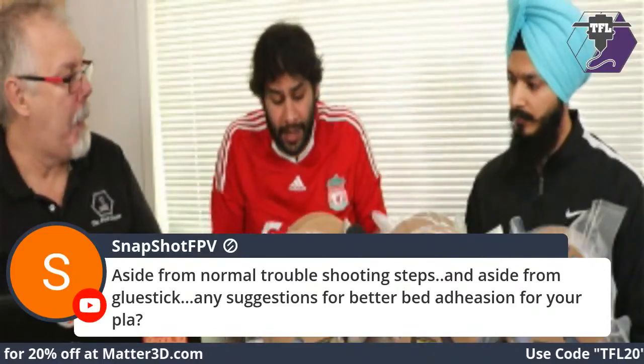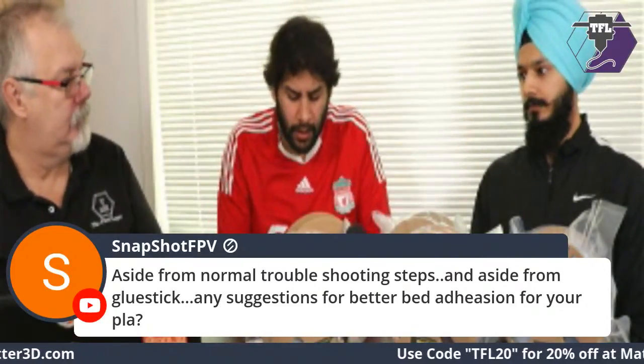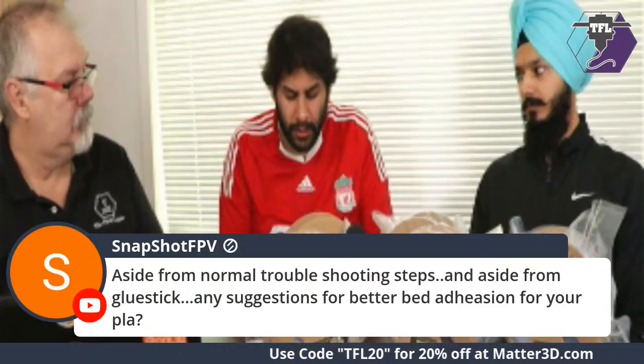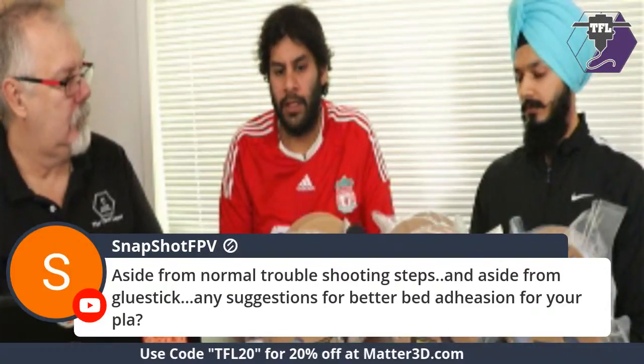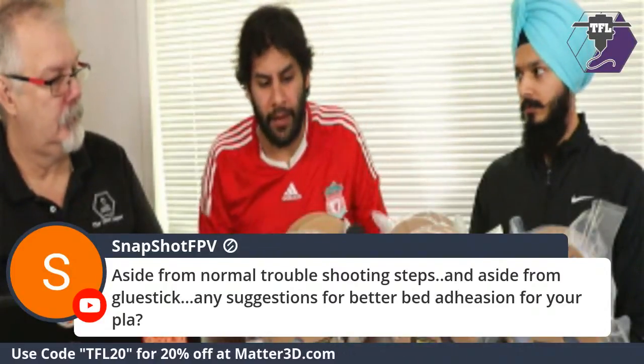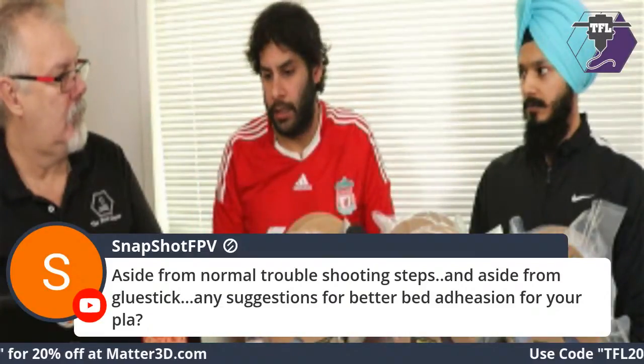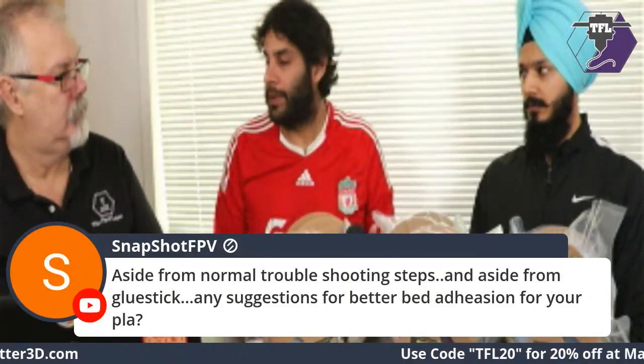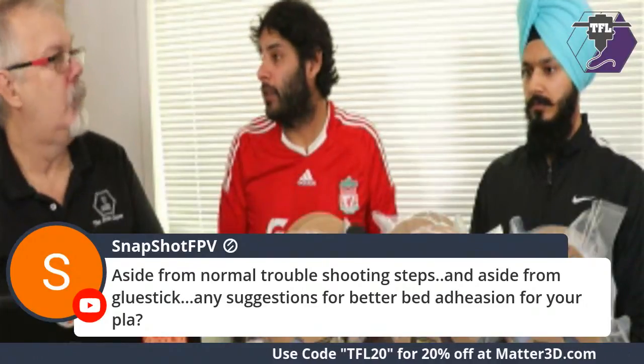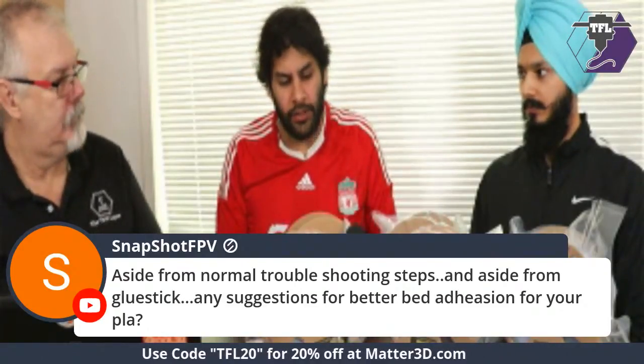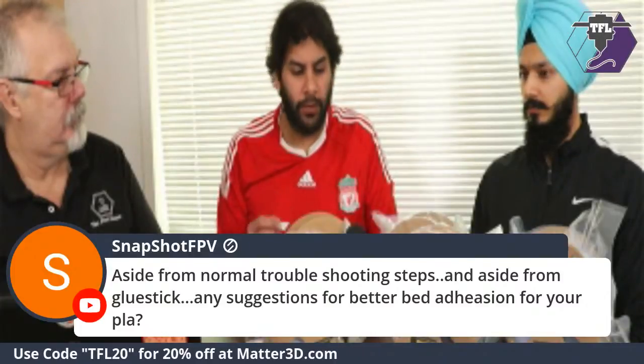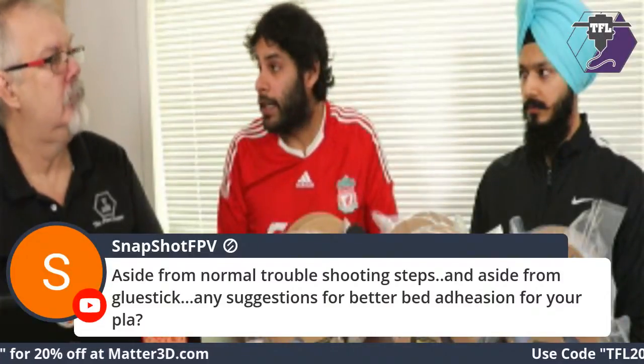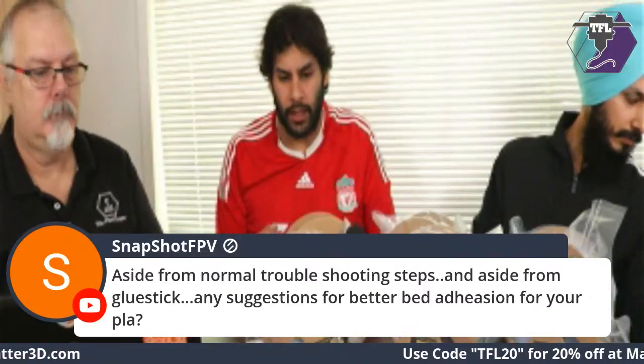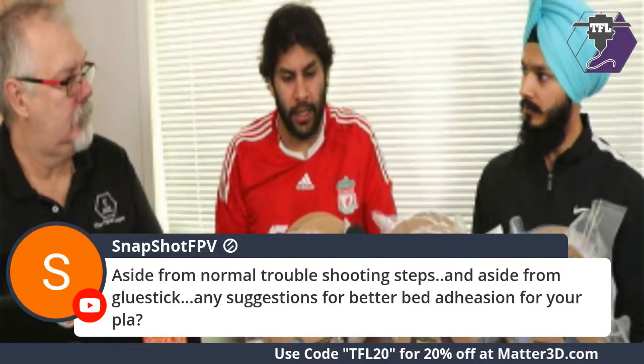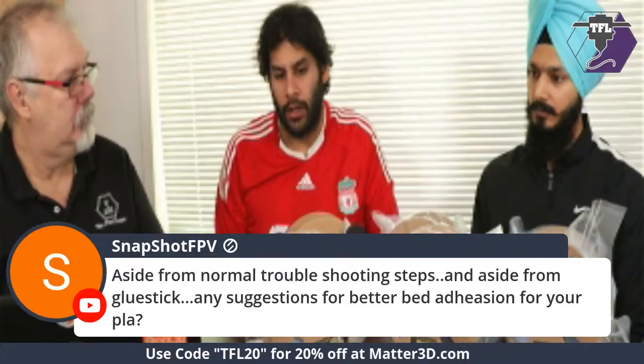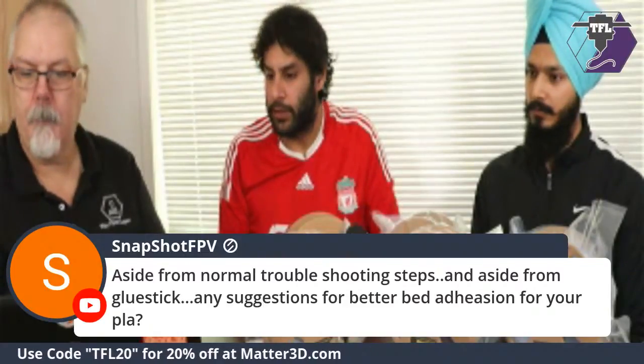I was going to say, warping has to do with the change in temperature with time. If you have a high heat capacity material like a PLA, it'll in general warp less than a low heat capacity material like ABS. But that being said, this 3D850 is designed specifically to warp even less, and that's because of its high crystallinity. It's not to do with anything else. It's just the high crystallinity and not having any additives like fillers put into it. Yeah, that makes a big difference.